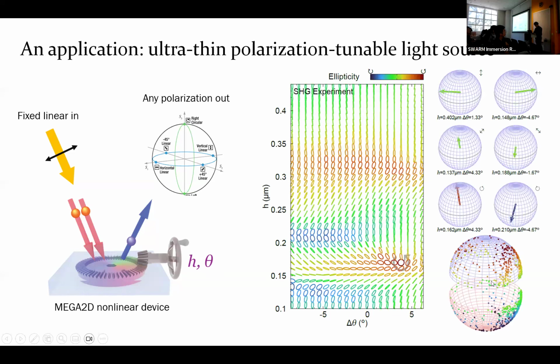And this is because around one of these singularities I mentioned earlier, the polarization of the light is highly sensitive, and well, it's rather complicated, but it's very sensitive to the change in H and theta, the twist angle. So just by playing these two knobs within a small range, we can change the polarization to any polarization we want. And some examples are shown here.